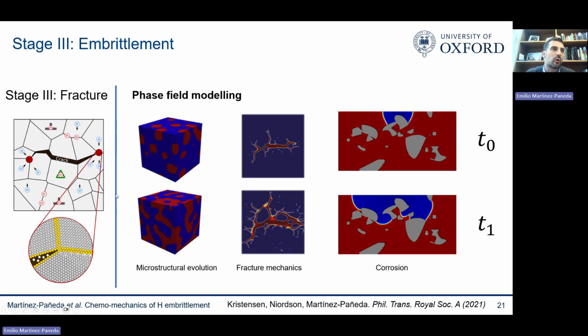This has been going on for quite a while. It was first proposed in the context of microstructural evolution and solidification, which is now by far the most dominant technique. It has also very quickly become the most popular technique to simulate cracking and fracture mechanics problems. You can see why: this is the output of a hydraulic fracture simulation, hence these complicated cracking patterns. You can see crack branching, nucleation of secondary cracks, coalescence of multiple cracks - very complicated cracking phenomena that we can only model thanks to these tools. There's no other way we could simulate such complicated cracking phenomena.